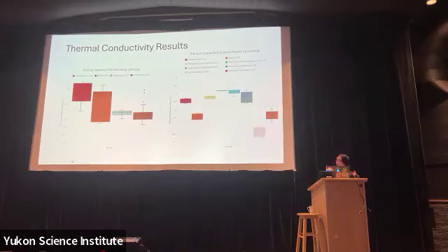So on this side, we have the in situ results. You can see the in situ results have a higher variability and generally a higher thermal conductivity within the well. And this is because of the fractures and that groundwater flow that we're seeing within those wells. And for the laboratory results, it's just the rock. It's the small 15 to 20 centimeter sample of rock that I'm able to test in the lab.